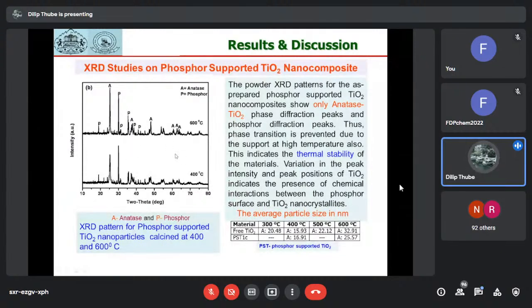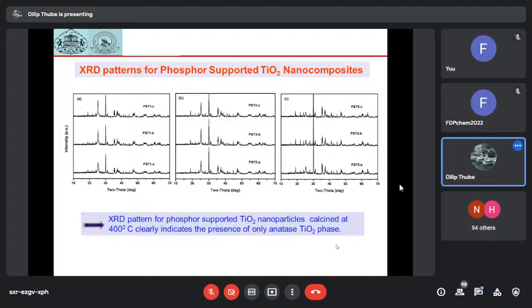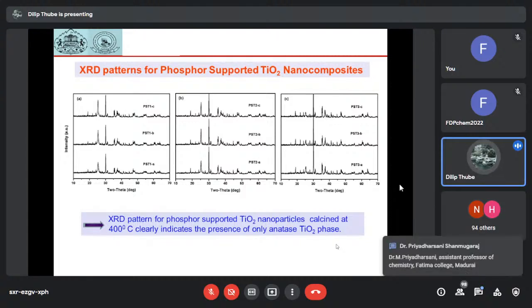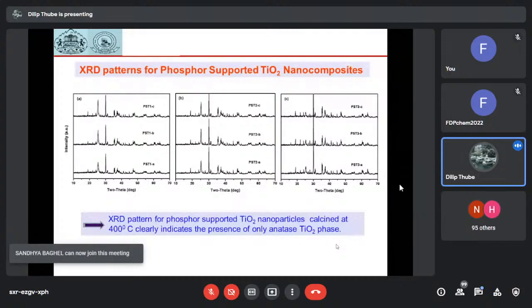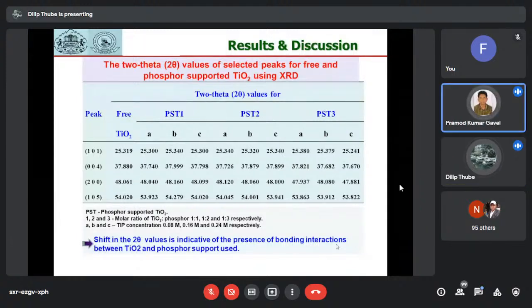From these various peaks, it is clearly indicated that the material is crystalline in nature, and by using XRD we can find out the crystallite size. Phosphor supported TiO2 materials have crystallite sizes ranging from 15 nanometers to about 25 nanometers. So these are nanomaterials which are synthesized and sintered at about 400 to 600 degrees Celsius. Various compositions have been prepared by changing the concentration of TIP.